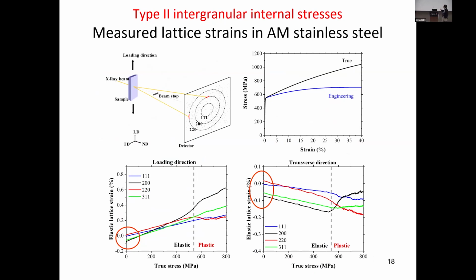Here I show you these synchrotron results for the AM stainless steel. You might notice that even without the loading, we can have non-zero lattice strain for certain grain families. That's because of the printing-induced residual stress that can significantly impact their behavior in service. Certainly, as we apply the load, we see the direct result from synchrotron, this linear and nonlinear behavior of different grain families. It's really data-rich. We also have the lattice strains from, for example, different grain families in the transverse direction, also correlated to their overall tensile stress-strain behavior.